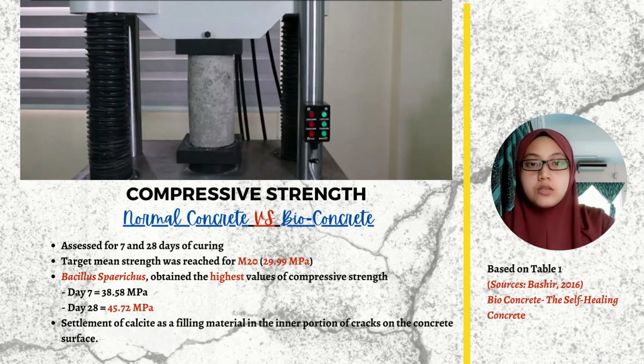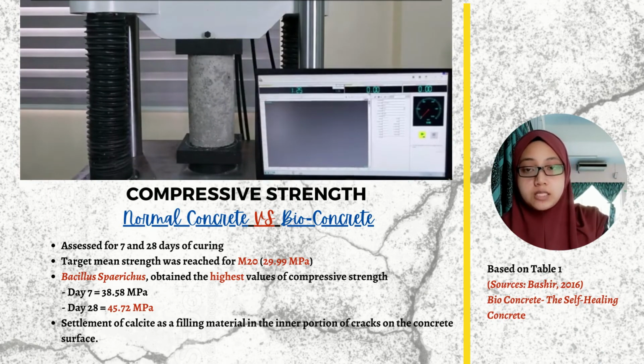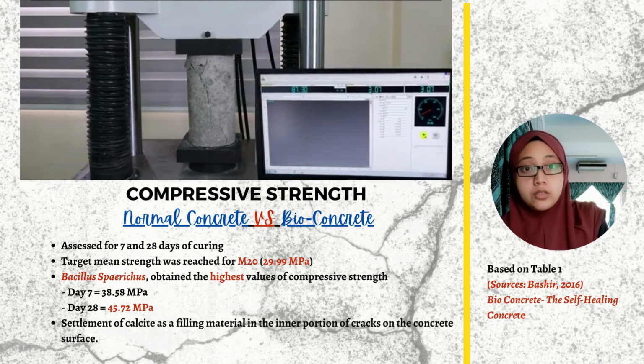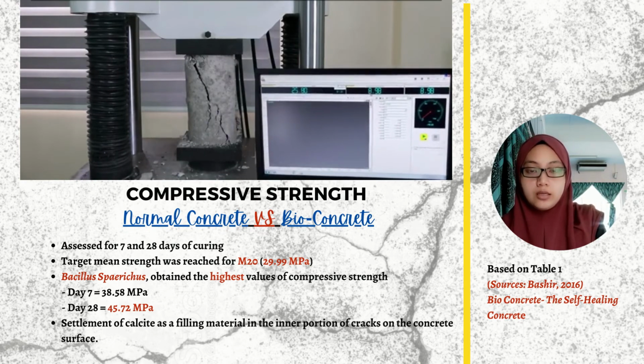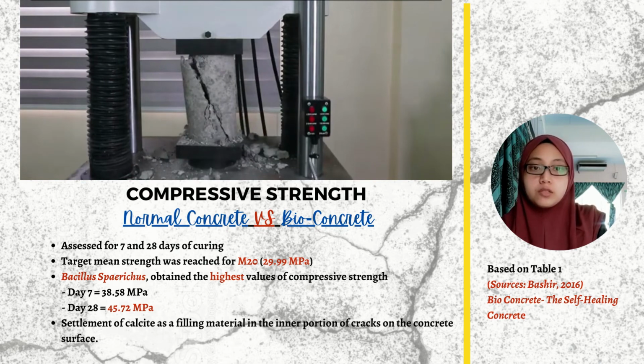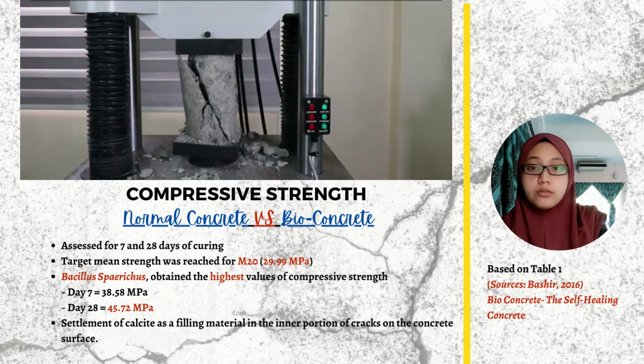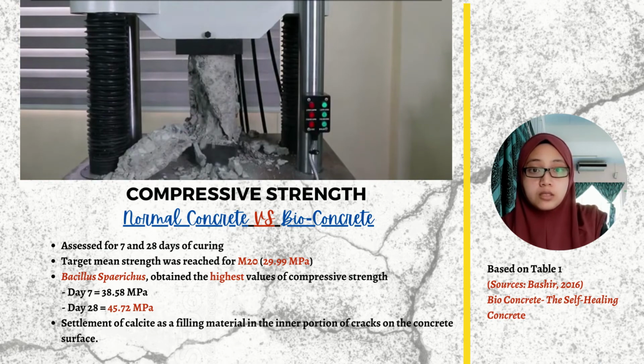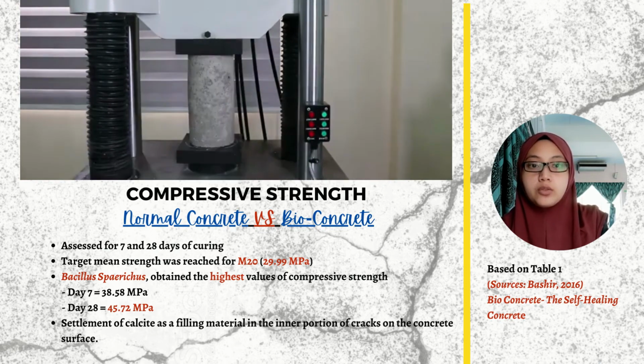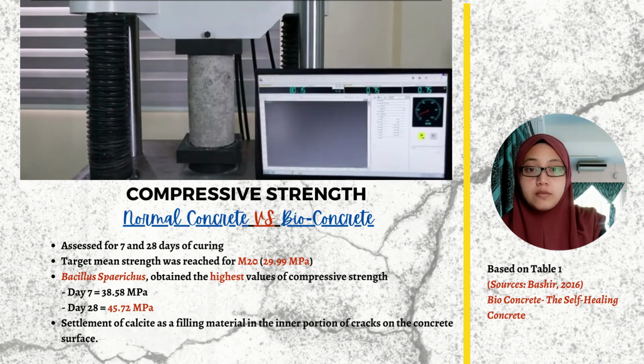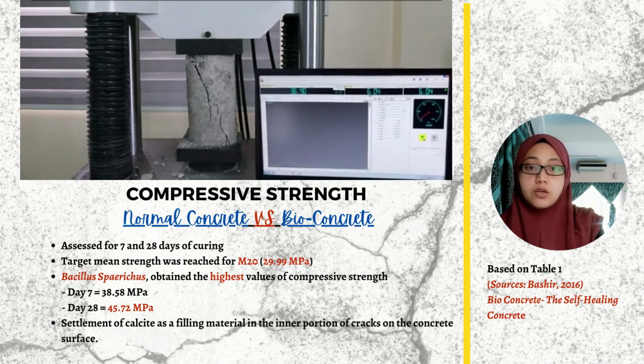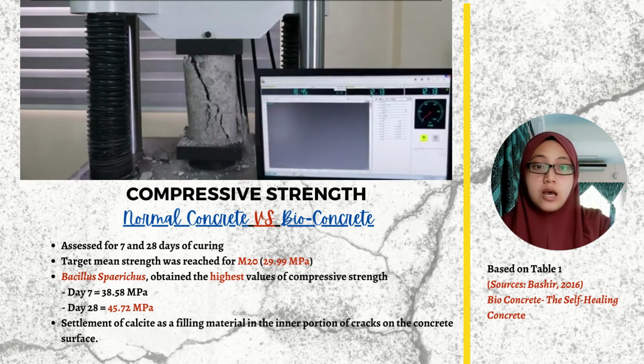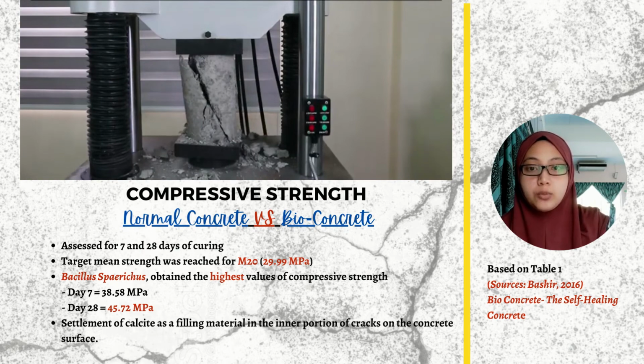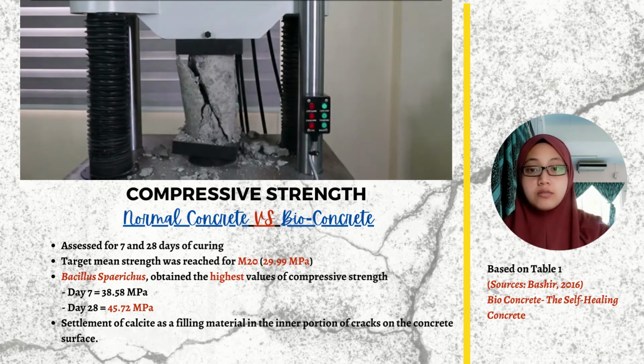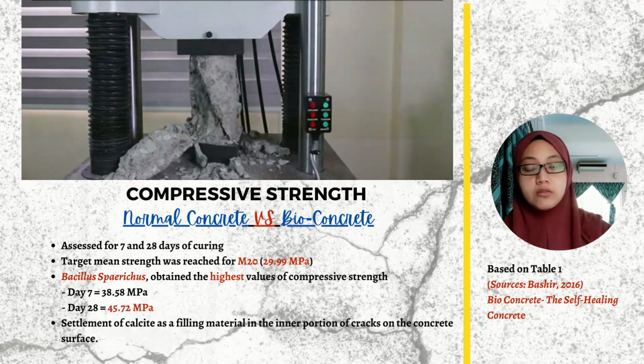The compressive strength was assessed for 7 and 28 days of curing of the concrete specimens. The target mean strength was reached for M20 grade conventional concrete, which is 29.99 MPa. There is an improvement in compressive strength for all types of bacteria used compared to the normal concrete. However, the result shows that using Bacillus sphaericus obtained the highest value compared to other bacteria, which is 38.58 MPa at day 7 and 45.72 MPa at day 28. The compressive strength was regained up to 52.42% higher at day 28 compared to normal concrete due to settlement of calcites as filling material in the inner portion of the cracks on the concrete surface.